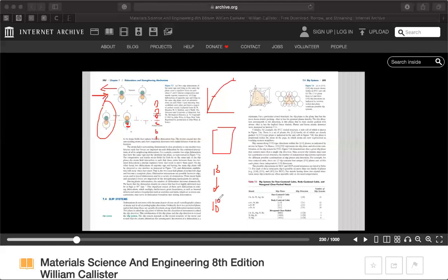in the material, according to the history of the material, according to what kind of stresses the material was exposed to, right? This is why, as I told you before, when you want to buy a material for its yield strength, you cannot just go to the table and look at the yield strength, let's say, for aluminum. You have to know also the history of the material, because the dislocation density might go from 10 to the power 3 all the way to 10 to the power 10, okay,